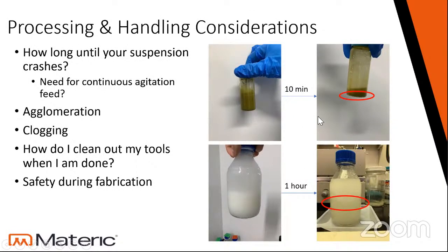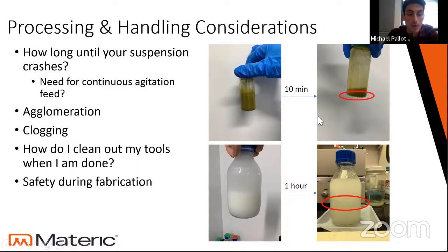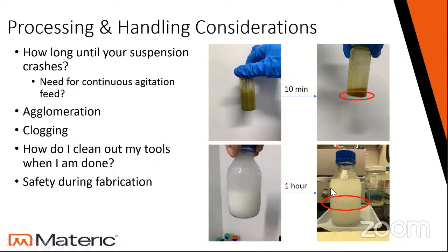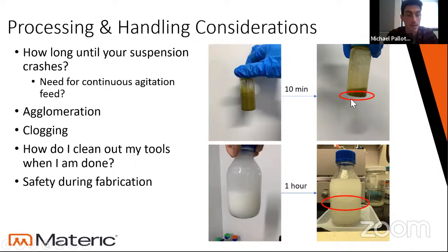So I'm going to start on the bottom right. On the bottom right, that white solution that has the 1 hour line in between, you can see visibly under that red circle that this emulsion does separate after about an hour. The way we're able to confirm that is we use a conductivity probe to see that we had one value when the solution was perfectly mixed, and then an hour later, that conductivity had completely dropped, which is confirmed by the emulsion being in two separate phases. So for larger solutions that we have to manually mix, we'll have about an hour of runtime.